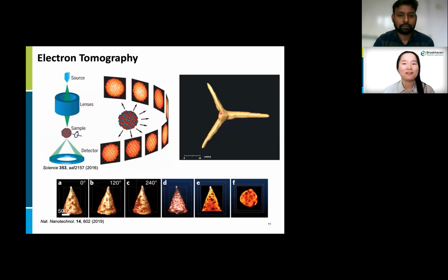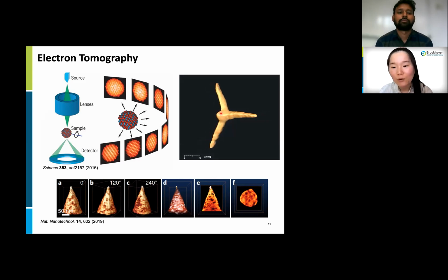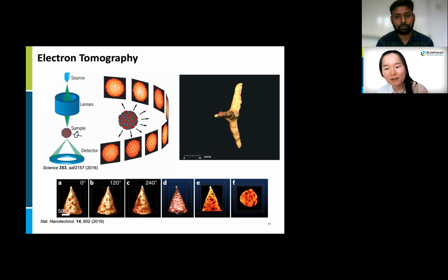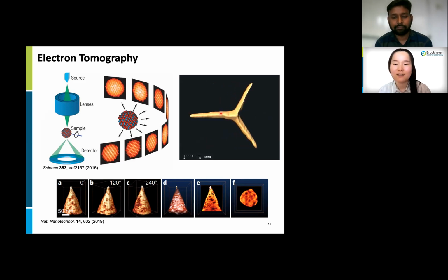I mentioned before that TEM provides 2D projection images of 3D objects, but with tomography, we can learn 3D structures also. We get images while tilting the sample at every 1 or 2 degrees. Then through computation, we can reconstruct the 3D structures. Here is an example of tripod-shaped palladium lead catalyst materials I made before.